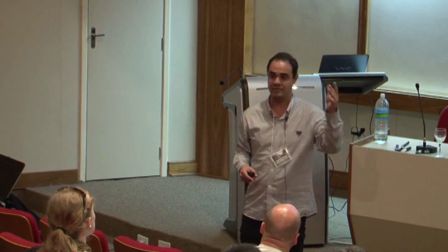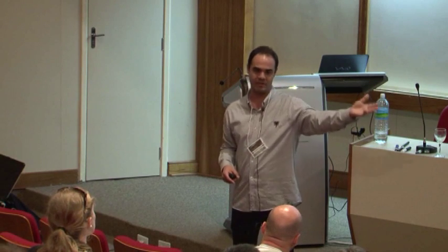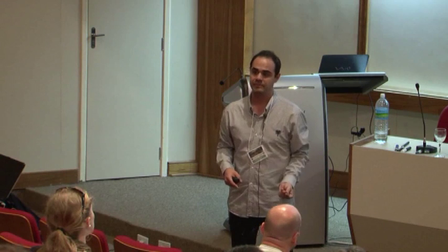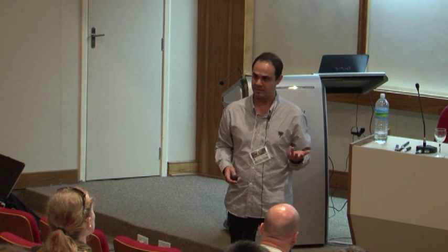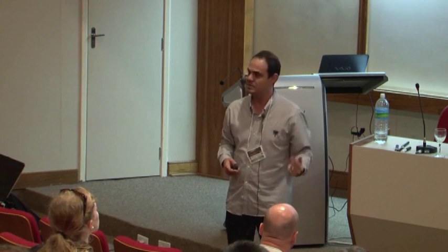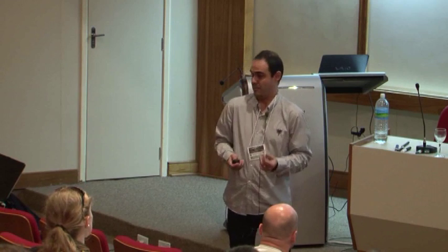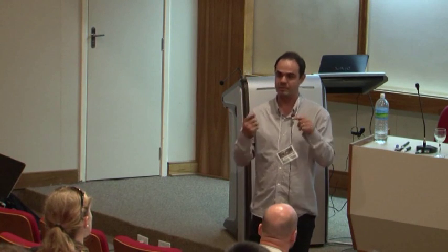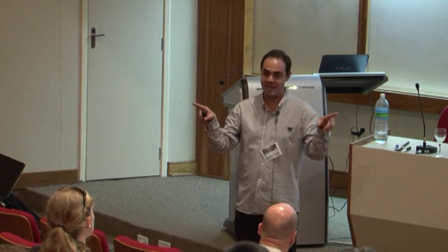Some of you will say, what interaction do we have in cerium that we don't have in the others? Kondo, right? The Kondo effect is on for cerium. So you say, oh, of course, so it's a change in T_K that is killing the magnetism for cerium. Why? Maybe not, because crystal field can have different effects in different J's.